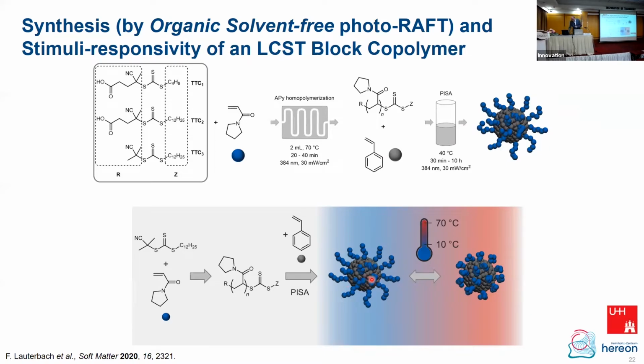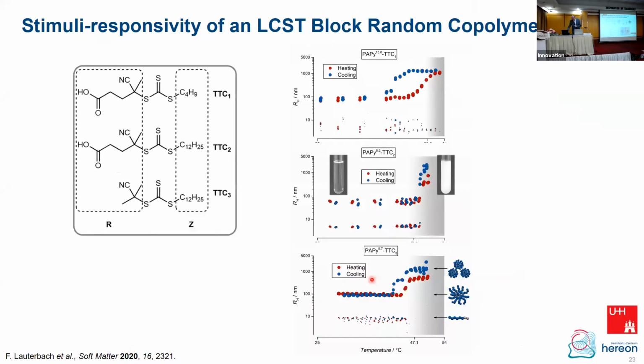And this is a stimuli-responsive system he generated, and he was playing with the type of RAFT agent he used. Depending on the hydrophilicity or hydrophobicity of the Z group, and the hydrophilicity of the R group, you can adjust the cloud point. So the more hydrophobic, the lower the cloud point, basically what you observe from the dynamic light scattering when you look at the hydrodynamic radius. And it's reversible, sometimes with hysteresis, but it's basically reversible.